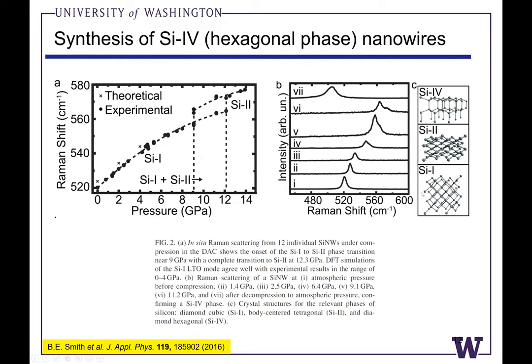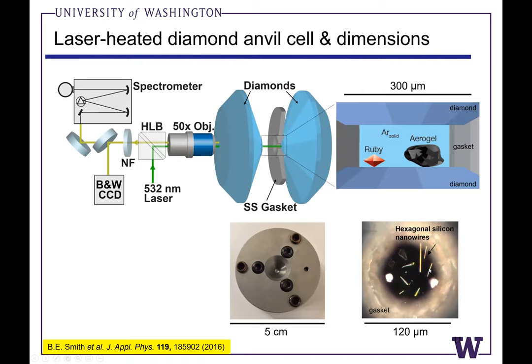I was excited about this result that we could start with a cubic silicon sample nanowire, compress the silicon one phase at high pressure and trace this with Raman spectroscopy to silicon two, which is tetragonal. And then on releasing pressure, we could recover silicon four, which is a hexagonal Bravais lattice. What's really interesting about the hexagonal Bravais lattice is it has a direct band gap. And we could make effectively hexagonal silicon nanowires, keeping the same morphology, the sort of one-dimensional linear morphology of silicon.